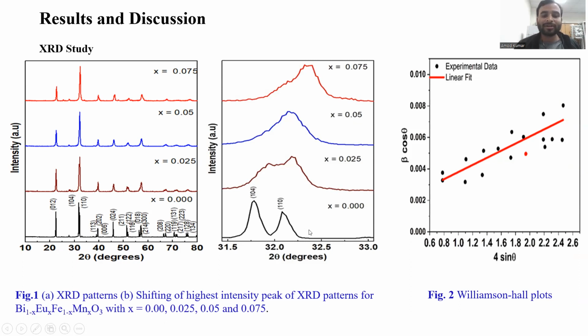In the lower doping, there is no doping, it's a pure BFO. Then it has two peaks, but after increasing the doping, the two peaks convert into one peak and sit at the right side, at a higher degree. It is due to the stress and strain and due to the phase change.